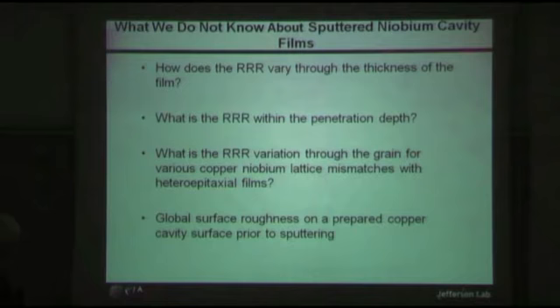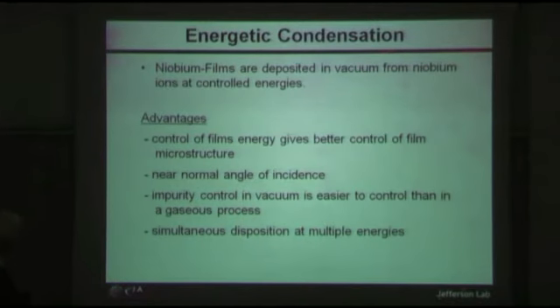With energetic condensation, we can avoid many of the problems with conventional sputtering. Here we're looking at just one form of energetic condensation, which is that of niobium ions deposited in vacuum at controlled energies. The two major differences between this technique and deposition by conventional sputtering are the energy added to the film as it's condensing layer by layer, and the lack of gas ion scattering and gas inclusion in the film.